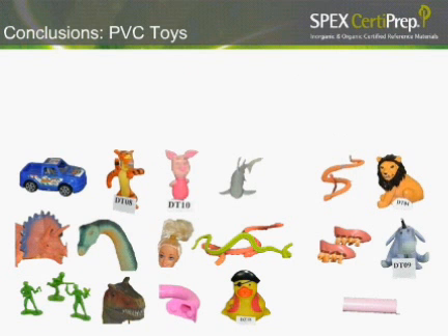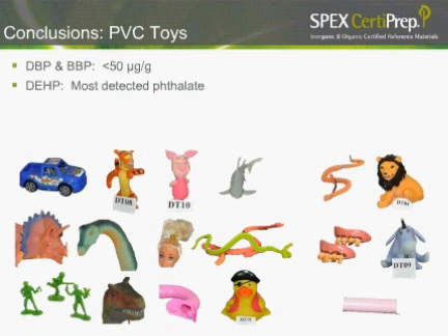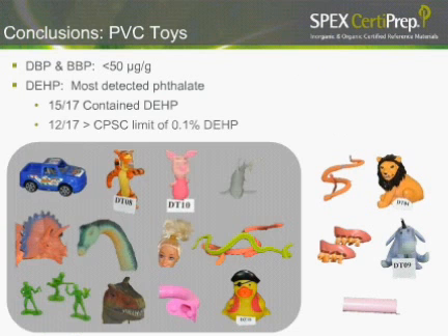So if we look at the conclusion of what we found in the PVC toys, we found small amounts of some of the other restricted phthalates, below 50 micrograms per gram of the DBP and the BBP. Our DEHP was our most detected phthalate, with 15 out of 17 of our toys containing the DEHP. We also found 12 of the 17 toys would be considered over the Consumer Product Safety limit of 0.1%.